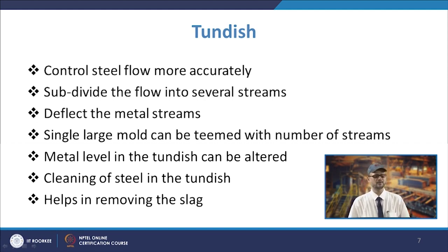Then you also have the possibility of the cleaning of steel in the TUNDISH. In the past it has been seen that sometimes the cleaning operation is also done in the TUNDISH. And even now we think of having the TUNDISH act in such a manner that if there are any inclusions they must float. So, the inclusions must be removed from the steel in the TUNDISH. So, it also works as the reservoir which will be looking towards minimizing the inclusion content in the steel. So, that we will see later.